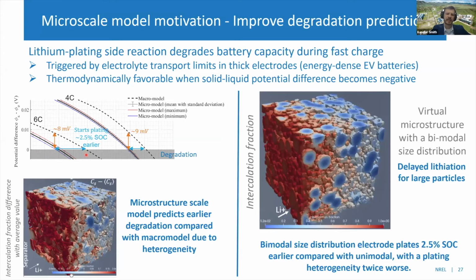And then we've done things like look at bimodal particle size distribution. So some manufacturers do this. They pack small particles together with large particles in order to get a higher packing density, a more volumetrically dense electrode. And we see that that increases the heterogeneity yet another 2.5% SOC. So a lot of these factors actually make the onset of lithium plating a little bit worse.